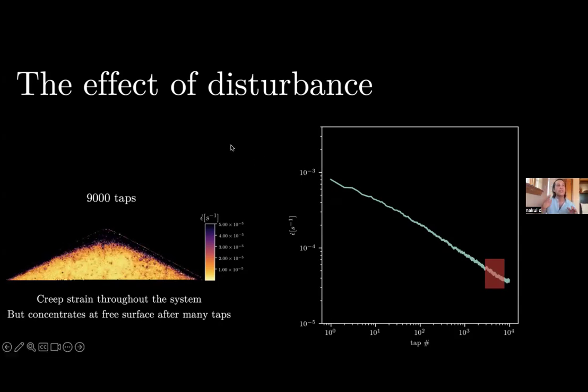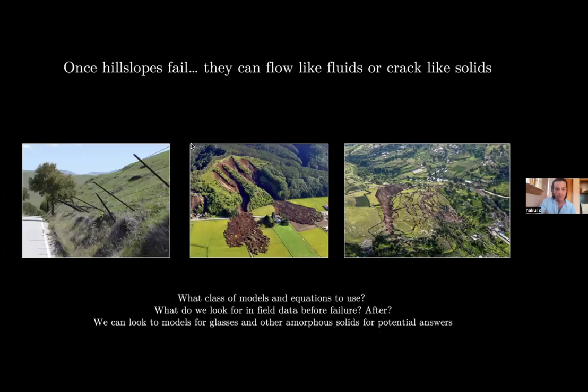So if creep under gravity alone is a kind of relaxation, when you're tapping the system, it's a kind of accelerated relaxation, right? By compacting the system, you can make it creep slower than if it were just sitting under the influence of gravity alone. So you can tune the rate of creep depending on the type of disturbance that you use.